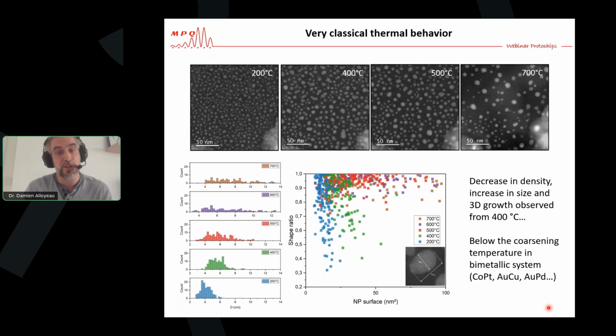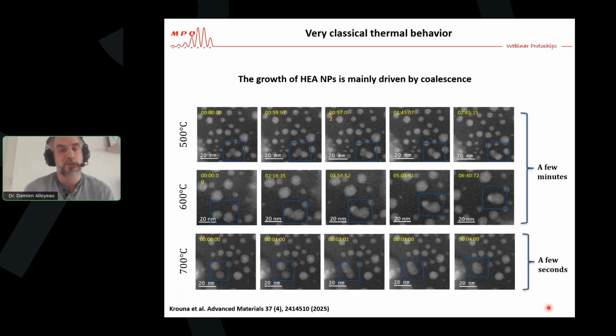So in fact, first conclusion, there is no sluggish diffusion in these finite size high entropy nanoalloys. The main mechanism driving the size increase of the particles is coalescence. And here I show you that at 500 or 600 degrees, it takes a few minutes to obtain the coalescence. At 700 degrees, it takes a few seconds. Very logical, because it's a thermally activated mechanism. What I want you to see here is that each time we have a coalescence event, we observe a strong contrast area in the nanoparticles that indicates segregation of the metals within the nanoparticles. Keep that in mind for the next slides.